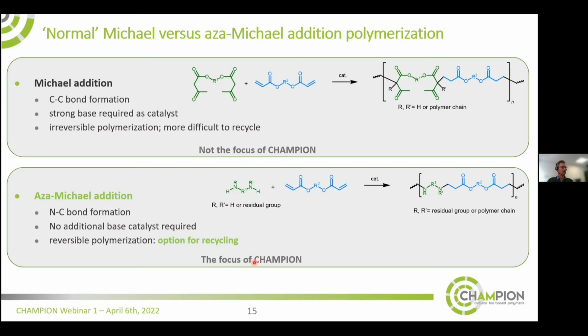So comparing the classical Michael addition that we've used in the railway elastomer application with the aza-Michael chemistry that we use in Champion, you see that classical Michael addition involves the formation of carbon-carbon bonds. You need a strong base, otherwise the reaction will not proceed. And what you end up, because you make carbon-carbon bonds, which are very difficult to break, you end up with materials that are more difficult to recycle. So classical Michael chemistry is not the focus of Champion.